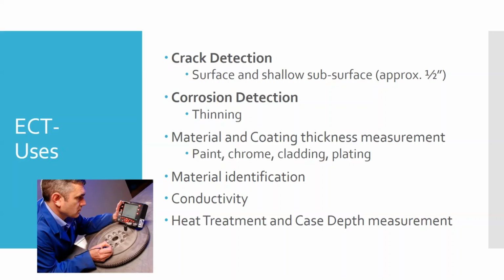The other thing that this can detect is corrosion. For crack detection, we can find surface and shallow subsurface cracks up to approximately a half an inch deep. And that's where the corrosion type of thing can take place, in that we can measure the thickness of a material. A particular area in aerospace where you'll see this, and you'll get to do this in lab, is a lap splice. You have two pieces of metal that are riveted one on top of the other. We all know that the area between the two pieces of sheet metal is prone to corrosion buildup. As that area corrodes, it's going to eat into the materials and make them thinner. And so you can detect that without having to pull that lap splice apart, take the rivets out, and actually see that.